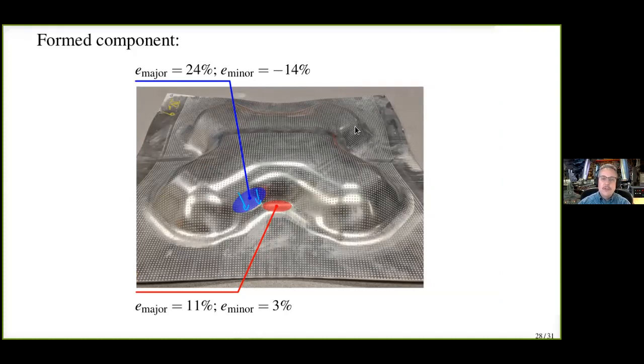Now, if we go to this region right here, this gives us a major strain of 11% and a minor strain of 3%, which is close to zero. This is a problem because it's very close to something we call plane strain. That is the stress state under which failure occurs most readily for most sheet forming applications. So in this case, this is where cracking would occur.